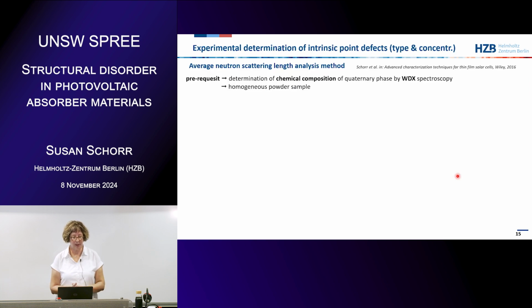So this is what we are doing mainly in the data analysis. We do the average neutron scattering length analysis with the prerequisite that we have to know the chemical composition very precisely and that our sample is homogeneous. That means if we have another phase, like another binary phase or ternary phase, this doesn't matter. But the quaternary main phase we study has to be homogeneous, otherwise it will not work.